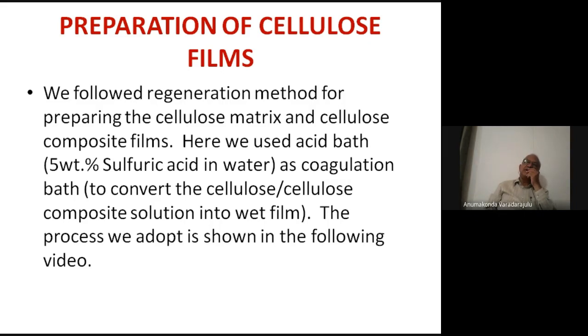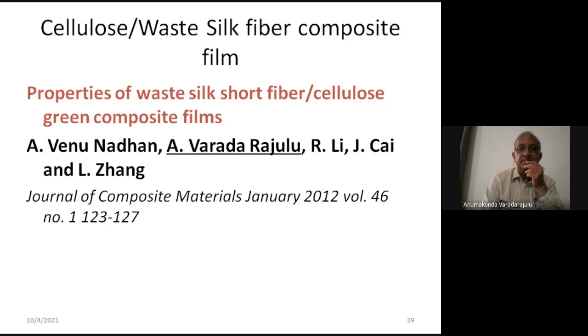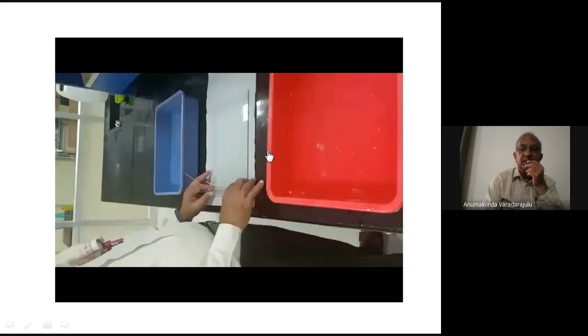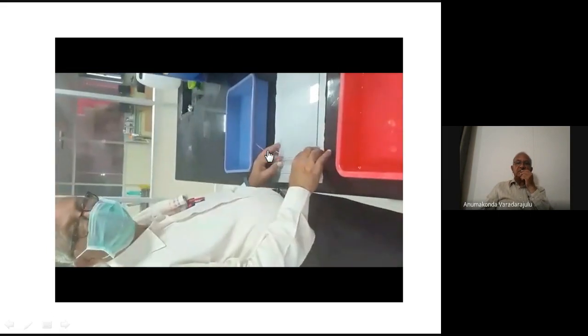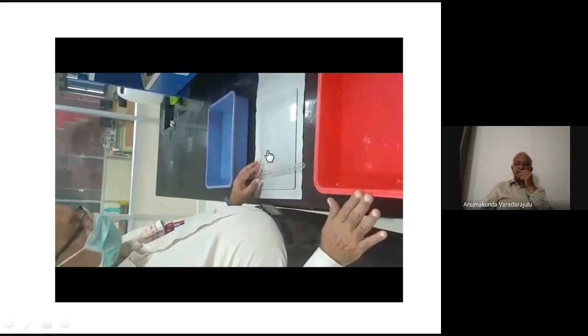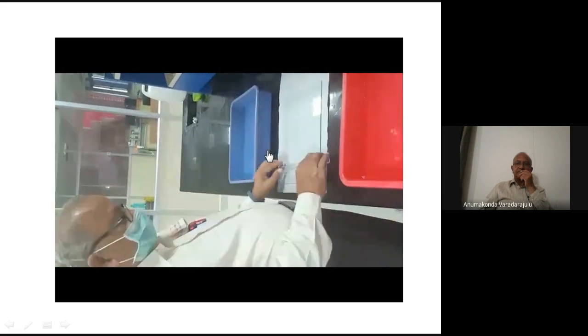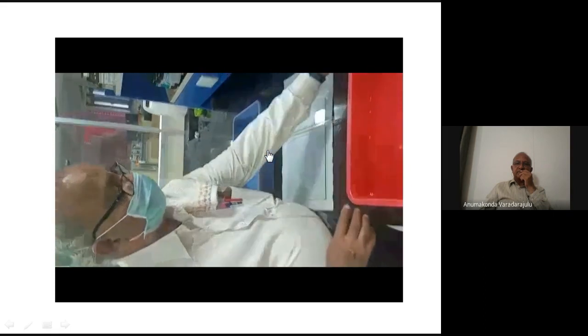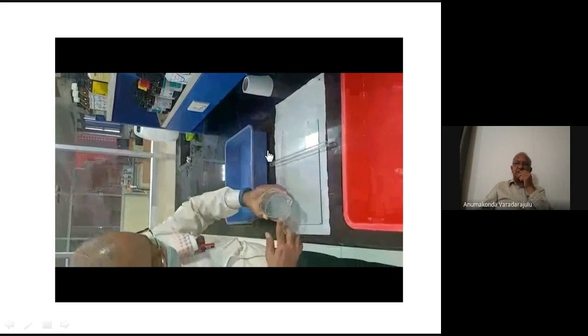But casting is again a difficult thing. We follow what is known as the regeneration method. We form the liquid film of the composite and then make it a solid by using a non-solvent. Because we used sodium hydroxide, we use an acid as the coagulation bath to convert the solution into a solid. So let me show a clipping of how we prepare the solution. It may be a matrix or a composite.